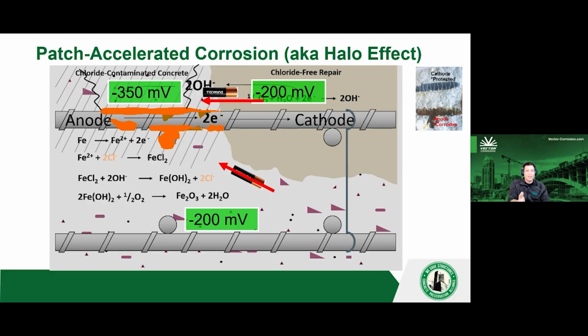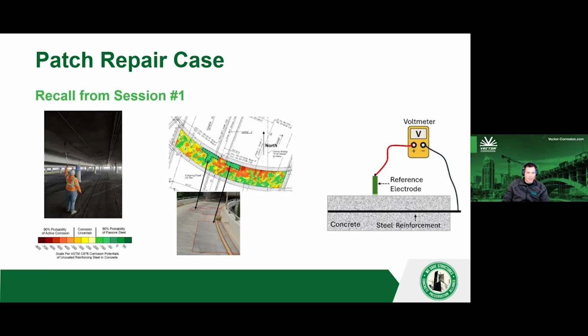And it's patch accelerated because you don't have the same time lag of needing the chlorides to diffuse through the porous nature of the concrete. It's already there, so you don't get potentially decades of time lag like you do with a new structure. And again, session 1, Pratik referred to this. Here's an example he showed where they did a half cell potential survey, and this owner did a patch repair while not addressing the area adjacent. And the area adjacent, you can see there's a lot of hot spots for corrosion, and I would expect that potentially they may have to come back in the next few years and repair that once it's corroded.